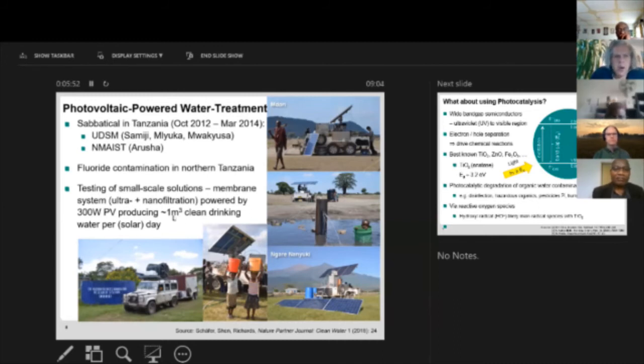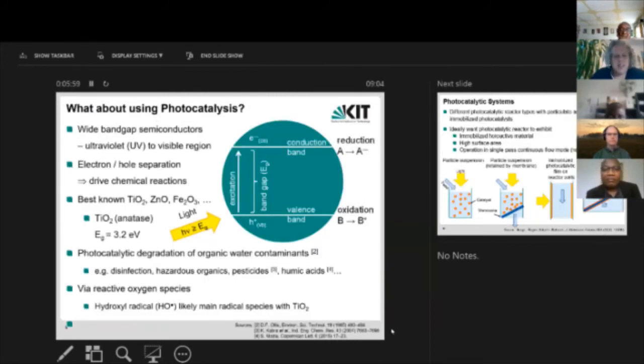So while that worked quite well, there's a bit of a materials emphasis lacking there. So that's taking engineering components off the shelf. But what can we do with photocatalysis? So largely this slide Lars has already covered the principles of. So we're using wide bandgap semiconductors to absorb at least the ultraviolet, hopefully some visible light. This electron hole separation shown on the right can be used to drive chemical reactions, both oxidation and reduction. The most commonly known ones are titanium dioxide, zinc oxide, iron oxide, copper oxide also there as well. We are going to be talking today about using titanium dioxide in the anatase phase, and the band gap of this is 3.2 electron volts.